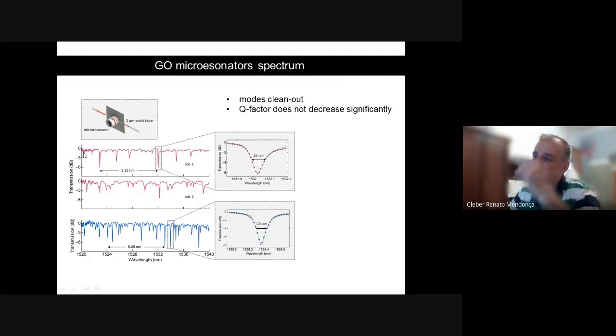And then what we see is the following. For the pure resonator, the resonator without the graphene, that's the spectrum we get. And for the resonator with graphene oxide, GO, you have much fewer resonances. And you see here that the Q factor is not that much different. The quality factor of the resonance is about the same, but the number of modes diminishes a lot when I incorporate graphene, and that's what we're calling a mode cleanup. So we are cleaning the modes by using graphene. So we have much fewer modes in our resonator.